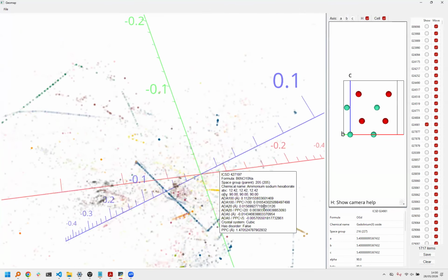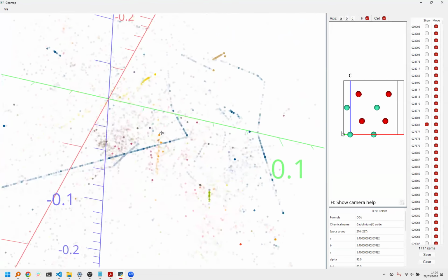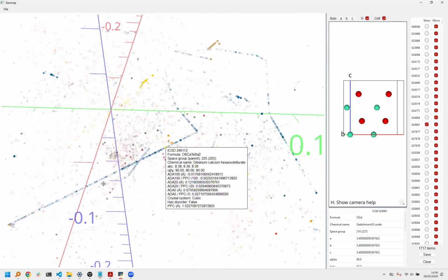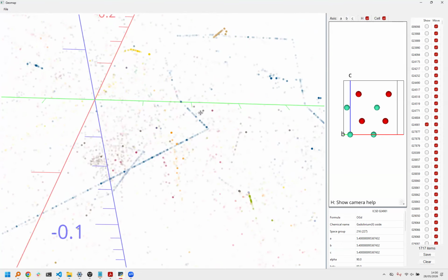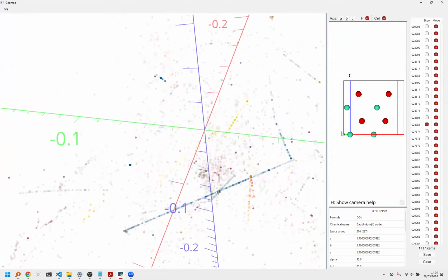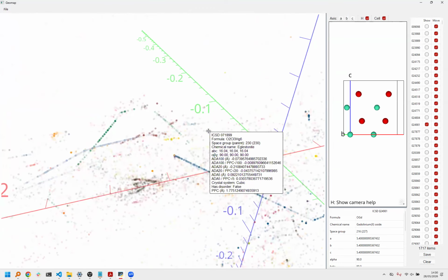And why is it, you might ask, that the lines sort of bend? Like, look at this here. Right, they don't bend, they very sharply turn. So we have continuity, right? This line here goes, and then it shouldn't, it suddenly turns. This is simply because if you keep deforming, then at some point certain nearest atoms will switch with other ones, and the rate of change will be different as you keep deforming. So it's continuous, but not smooth, I guess, right? These movements. And the next question I want to answer, but I think I'm going to show another plot.